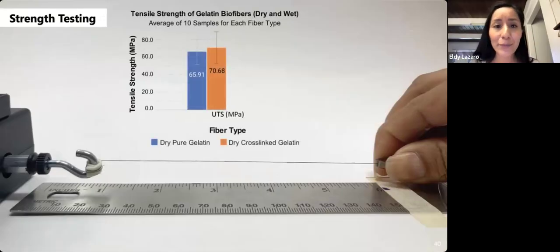And for those interested in the mechanical properties, based on the cross-section of the fibers, which I will show in a minute, they are very thin, like hair. We noticed that in tensile strength the fibers are pretty strong, very close to PLA, the filament for 3D printing. That was very promising, and it led to new projects that are happening in the lab right now, developing 3D printing material with gelatin and other biomaterials.